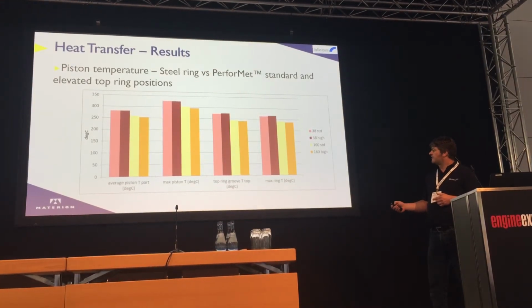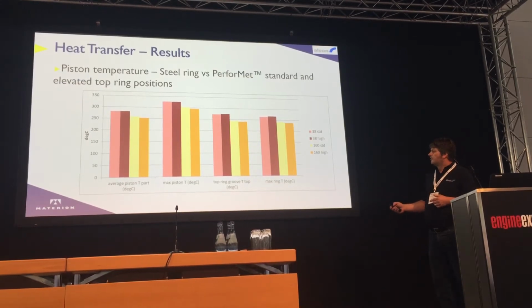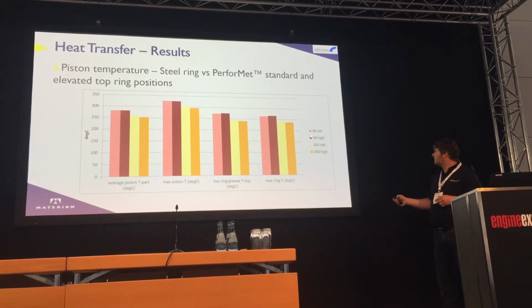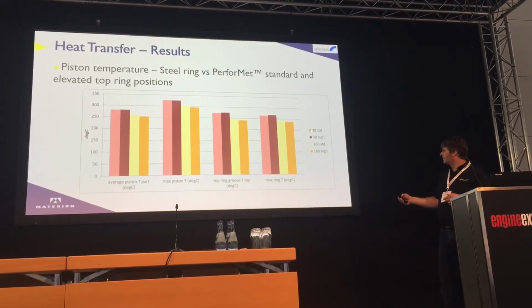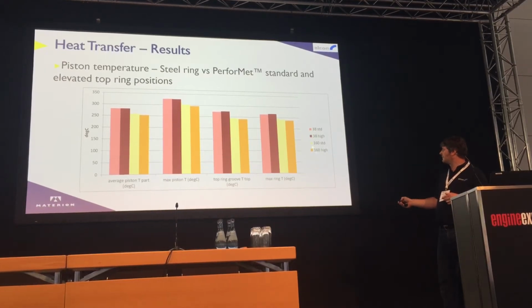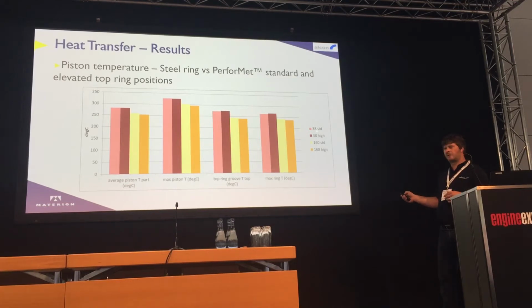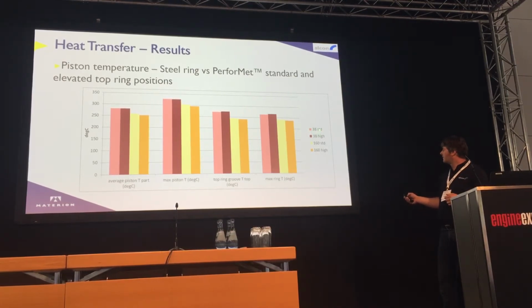This is an interesting graph again. So basically, we looked at 2 different rings, the standard ring at 38 watts per meter Kelvin and the new ring at 160 watts per meter Kelvin. And we looked at the ring in 2 different positions, a standard position and also a higher position, so we moved the ring up.